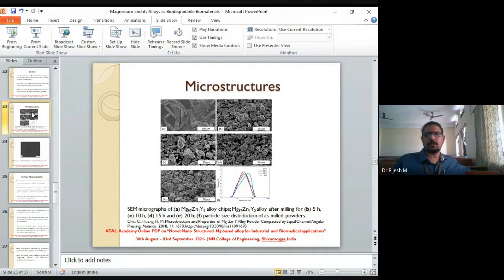Microstructures. This is the microstructure of various particles. When you're doing a ball milling process, you can see the particles getting fragmented. This is basically magnesium zinc yttrium alloy chips in the beginning, then after milling for 5 hours, 10 hours, 15 hours, and 20 hours. You can see the particle size distribution in the curve, and we can see the particle size reduces as the time goes on increasing.